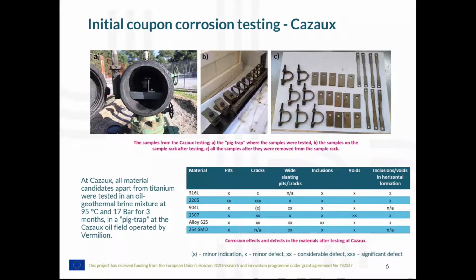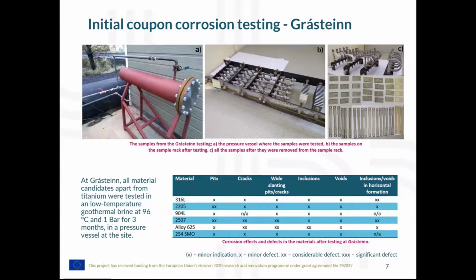And similar as for Reykjanes, we see various defects in all of the samples, but many of them are as well attributed to manufacturing. And taking that into account, the 2 best performing materials were the 254 SMO and 904L, which are both highly alloyed stainless steels. And the third and last initial coupon corrosion testing was performed at Grásteinn, which is also